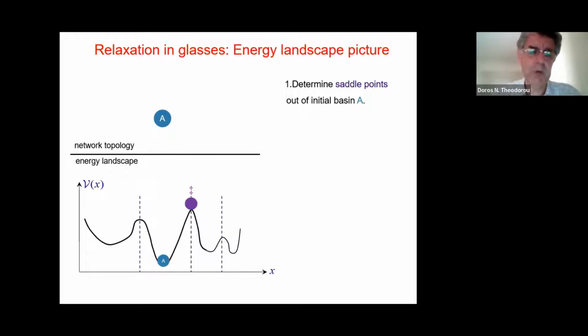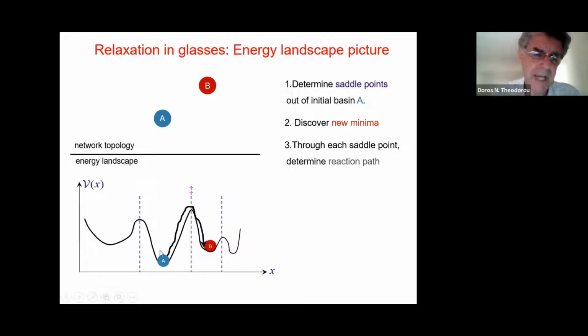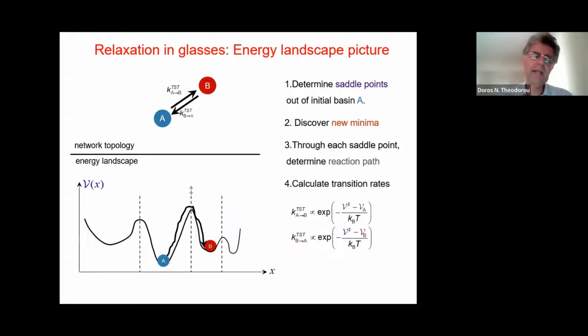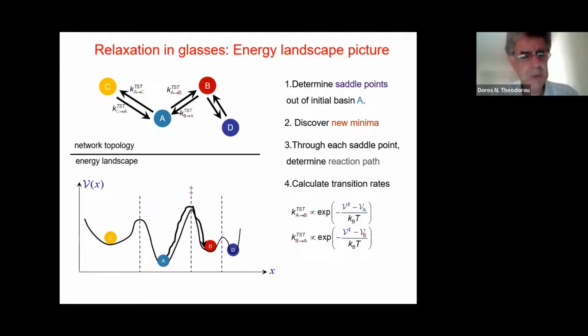Having determined one saddle point, we can then undergo a steepest descent construction in energy and go to another minimum on the other side. So we have two minima, A and B, in this example, which are connected across a saddle point. And we can construct the entire reaction path or transition path that leads from minimum A to minimum B. Having now these properties of the reaction path, we can use harmonic transition state theory to calculate rate constants for the transition from A to B and from B to A. And we can repeat that for other transitions leading, for example, from A to C, or transitions leading from B to other minima, D in this example. So gradually, we can let the system explore more and more minima, starting from a given minimum A, and at the same time, calculate the rate constants for transitions between pairs of these minima.